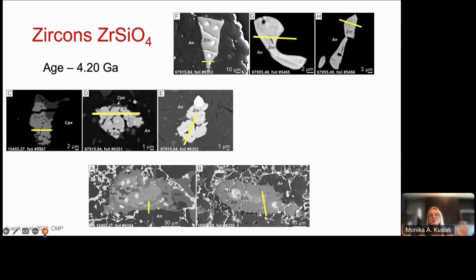So this is the image which puts together all our morphology of zircon. In the top row, regardless of the sample where they come from, I'm going to treat them now by features, not by specimens, especially since all the ages were 4.2. They were very, very uniform. But we can see that the zircon doesn't look uniform. We have at the top row idiomorphic and subhedral zircon grains, then granular zircon, and then zircon rim around baddeleyite, and all of this in anorthite.